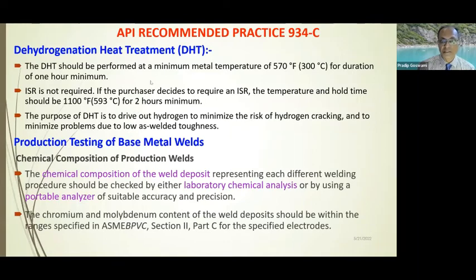And as you see here, the DHT or dehydrogenation heat treatment is mandatory for these vessels also. If it is done, it has to be done at 300 degrees centigrade for 1 hour as a minimum requirement. ISR, intermediate stress relief, is not required for these vessels, but instead of the ISR, the fabricator has the privilege to resort to DHT. However, if the end user or the purchaser decides to impose an ISR, then the requirement is 593 degrees centigrade for 2 hours as a minimum.